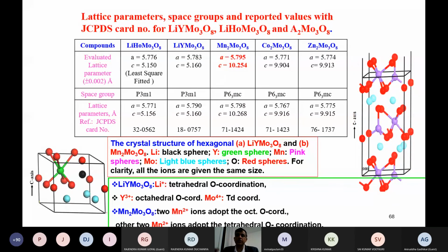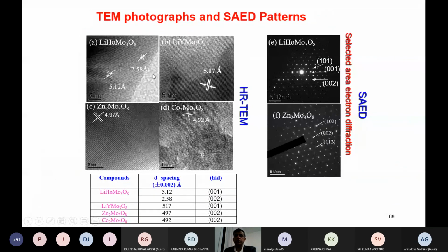As a metallurgist or materials engineer, the X-ray is very useful. We can evaluate the lattice parameters and compare with JCPDS patterns, or sometimes some materials are not really matched, and you can calculate values nearly close to the materials we prepare. Again, remember, for example with holmium or manganese, sometimes the c axis is expanded, that's why we can see an elongated c. Depending on the lithium and holmium, we can get A and C values that are lower. Again, you can do TEM. These are crystalline materials, and with the patterns we can index things. Based on XRD as well as TEM, we can see the d-spacing, etc.